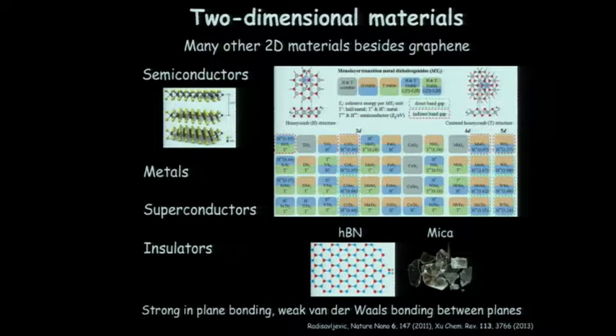So we have graphene, which is going to be our semi-metal that we're going to be probing. And then the idea is to couple it with a range of other materials. So we can have everything from semiconductors, if we use things like tungsten selenide or molybdenum sulfide. We can have metals or superconductors, niobium selenide, other ones like that. And then insulating materials. So I'm going to talk quite a bit today about what happens when you couple graphene and boron nitride. This is a material with the same lattice structure as graphene, but instead of having carbon atoms, you have boron and nitrogen. And so the asymmetry there gives a large band gap.